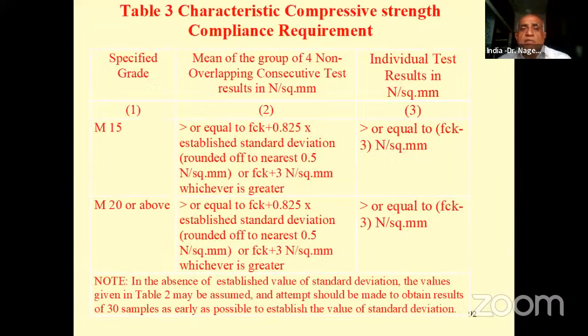Now this is a table which says if it is M20 and above, the characteristic strength is fck, and fck plus 3 is the acceptance criteria. That means if it is M20 grade of concrete, you should get 23 Newton per mm square strength. Why do we expect so much more than 20? Because we have designed a concrete mix of M20 for a target strength of around 28 or 29. When you are designing the concrete mix for 28 or 29 Newton per mm square, can't we accept at least fck plus 3 in sight?